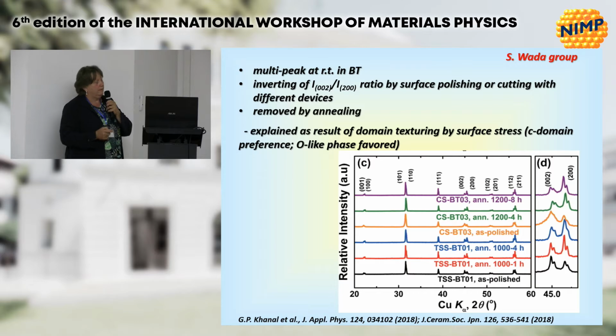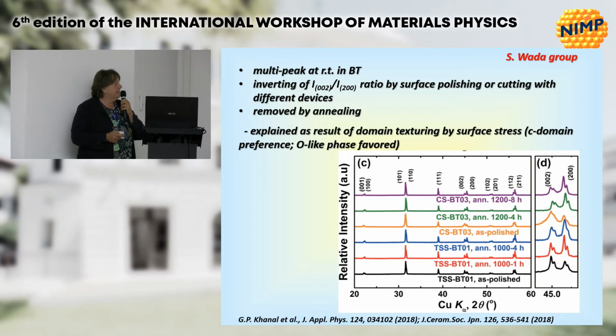We are not chemists, but we started 10 years ago to prepare samples. We have doubts about the purity, about the method, about the stoichiometry and so on. But at the same time, in the group of Vincenzo Buscaglia, they were preparing barium titanate and everything was orthorhombic. And then they realized that they had just changed the cutting machine for the ceramic. So it was due to a specific cutting machine that was different from the previous one. So no tetragonal barium titanate was obtained at that time.